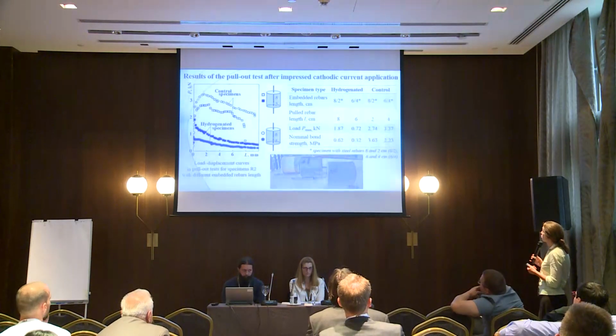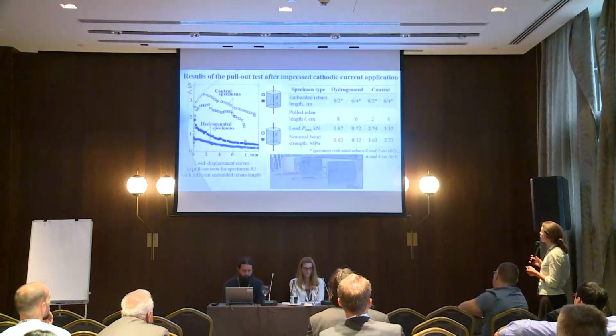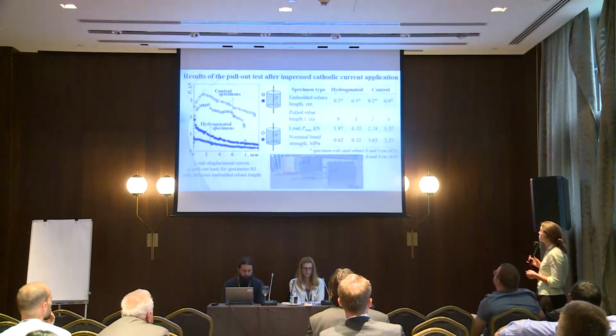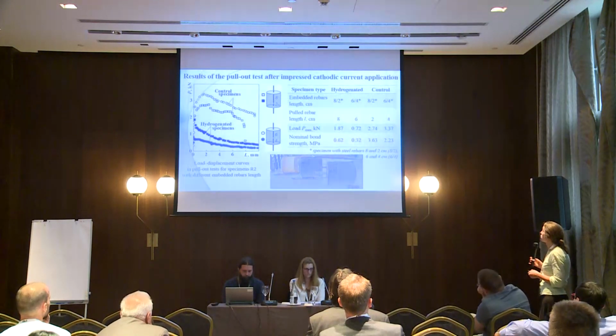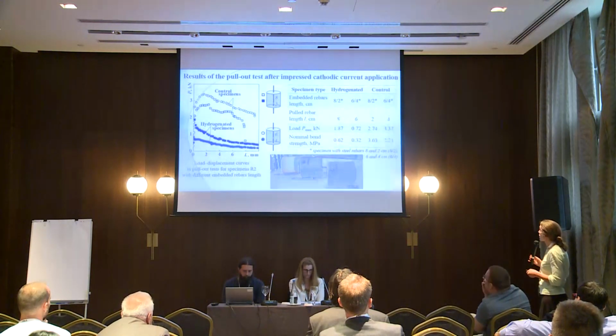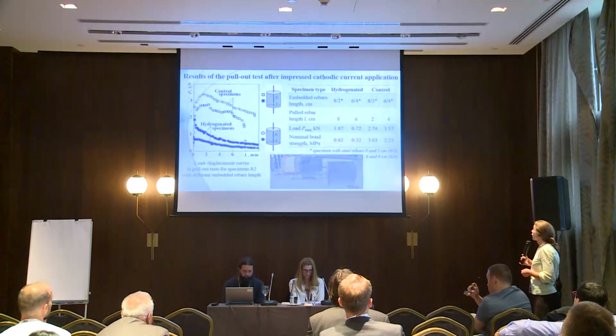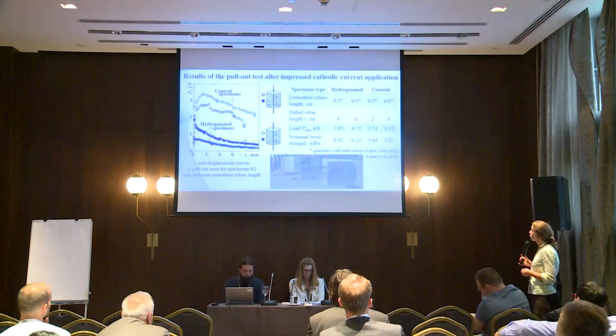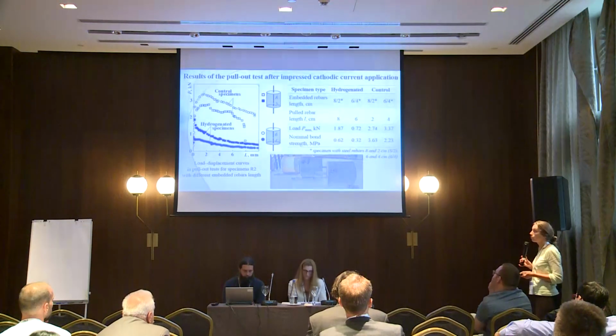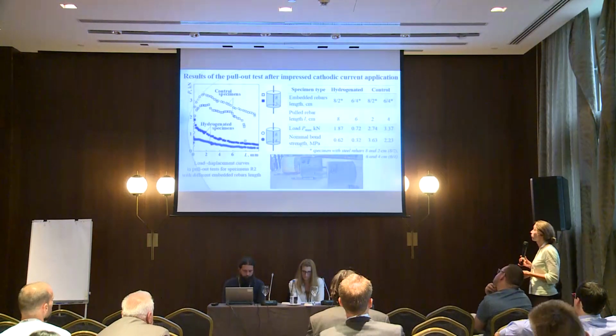In spite of data scattering, conclusions could be drawn that bond stress is essentially lower for hydrogenated specimens. So it indicates an essential bond weakening due to hydrogen charging of the specimen.